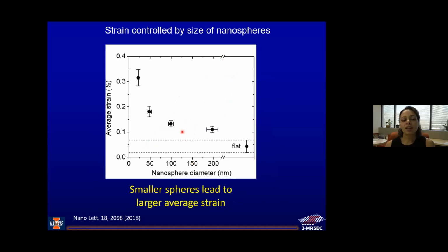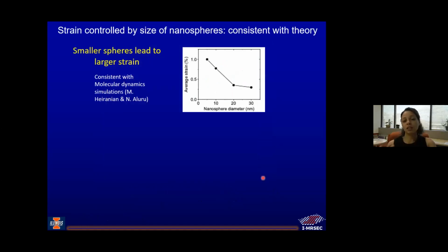Okay, and if we plot this average strain as a function of nanosphere diameter, we can clearly see that the smaller spheres lead to larger average strain. Okay, so this is something that we talked to theorists about. It turns out to be consistent with theory. So this is a molecular dynamics simulation by Narayan Aluru's group, our collaborator here at Illinois, and they showed that the average strain as a function of nanosphere diameter indeed got larger as you went to smaller size nanospheres.